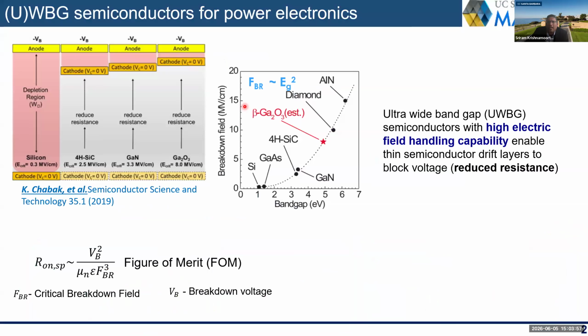So the idea behind using wide bandgap materials for power electronics is the fact that when we increase the bandgap of a semiconductor, it can generally hold much higher electric field across it. So going from the traditional power semiconductor, which is silicon, to say silicon carbide and gallium nitride, you go from a couple hundred kilovolts per centimeter to about 3 megavolts per centimeter. And so as the bandgap increases, the breakdown field goes roughly as the square of the bandgap. And so the electric field handling capability of a wider bandgap semiconductor is significantly higher than silicon.